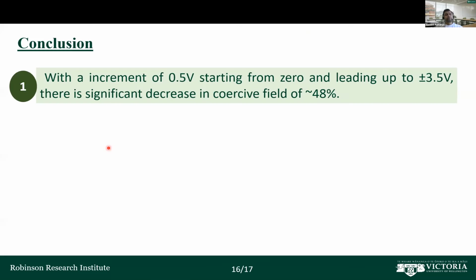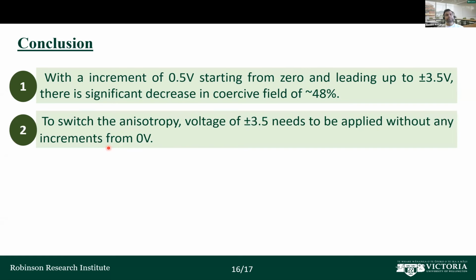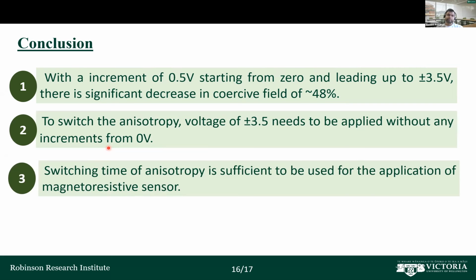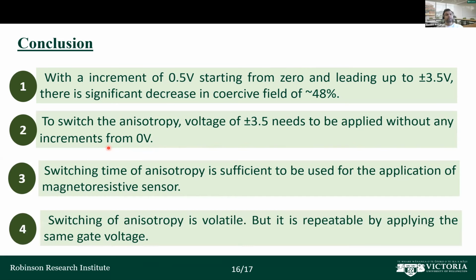So in conclusion, when we apply voltage at an increment of 0.5 volt in our ionic liquid gated stack, we were able to decrease the coercive field significantly, up to 48%. On the other hand, when we directly apply a voltage of plus or minus 3.5 volt, we completely change the anisotropy from in plane to out of plane direction. The switching time of the anisotropy was also really low. It is less than 1 minute for both directions, and that should be sufficient to use for the application of the magnetoresistive sensor. The switching of anisotropy is volatile, but it is repeatable by applying the same gate voltage as we have seen previously.